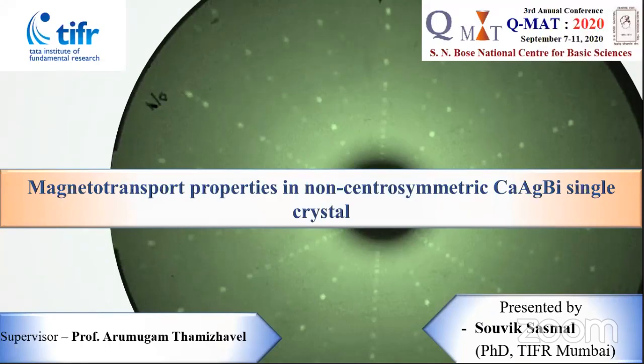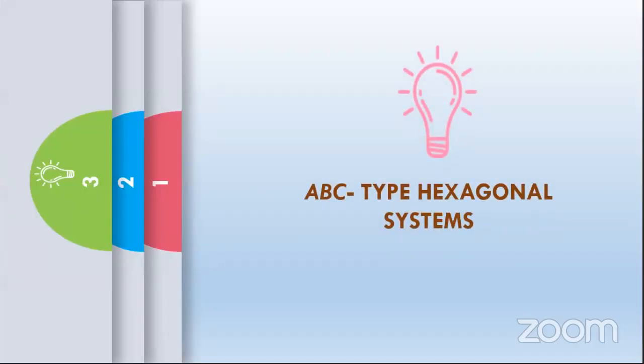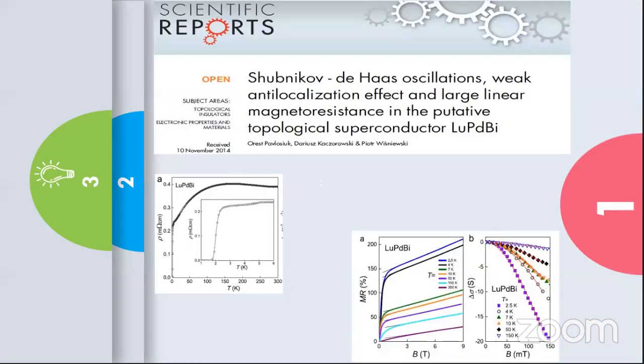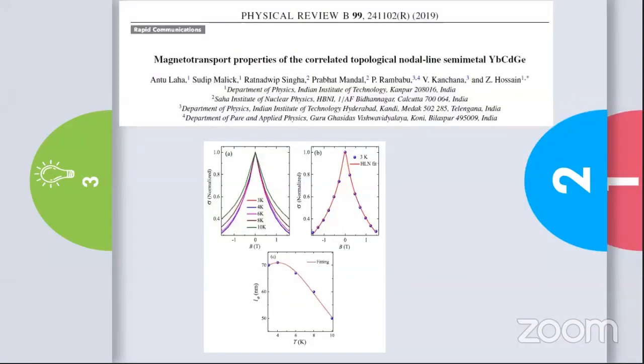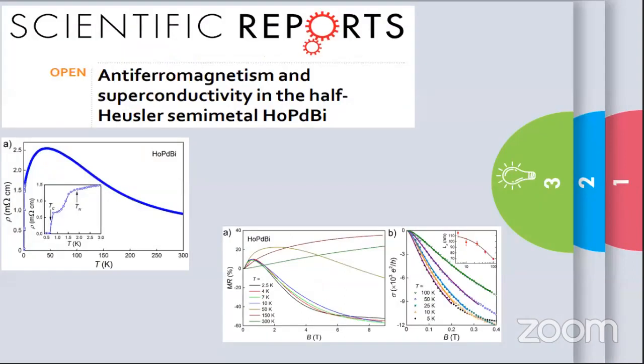Yeah. So this is a great opportunity to talk about crystal growth of calcium silver bismuth and the magnetotransport properties. First, this is an ABC type hexagonal crystal structure, and this kind of hexagonal crystal structure shows different interesting properties, including in LuPdBi, the superconducting transition at a low temperature near 1.8 K, and weak anti-localization properties, as well as YbCdGe, the weak anti-localization, and HoPdBi, as well as superconducting transition and weak anti-localization property.